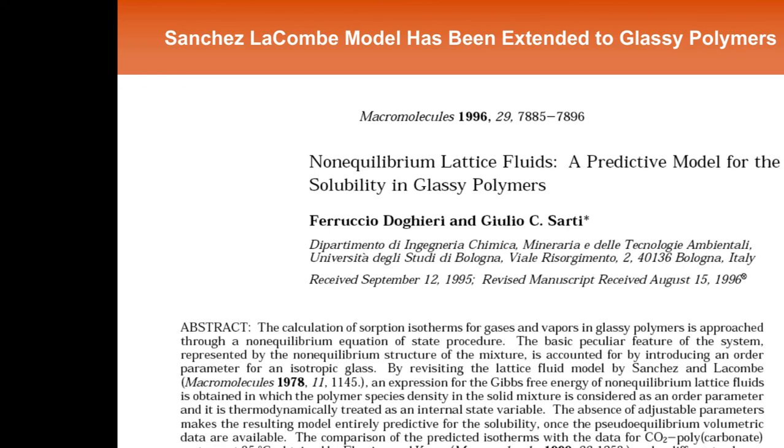It's a phenomenon known as antiplasticization. It's the word you'll find in the literature. What happens is that you'll see effects in things like mechanical properties. If you sorb a small amount of a penetrant into a polymer where it increases the density of the polymer, it makes the polymer stiffer, right? So it's not just transport properties that change; it can change all the dynamic properties of a material, including its mechanical properties.